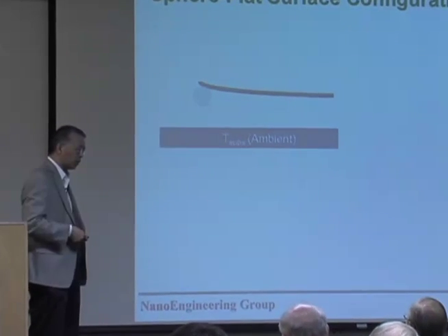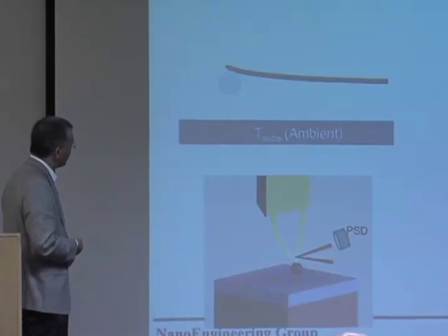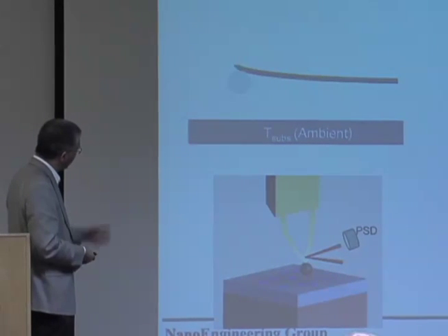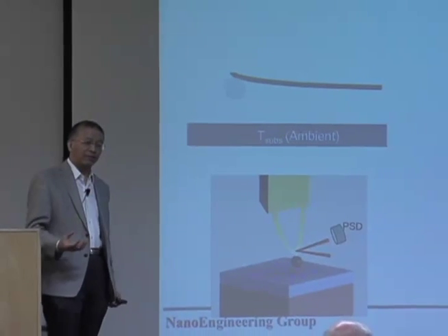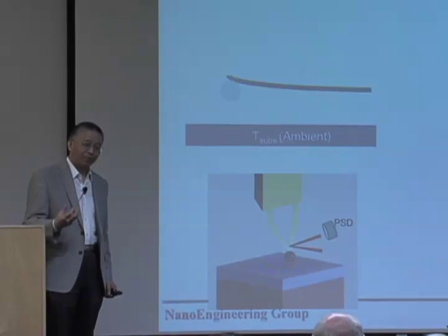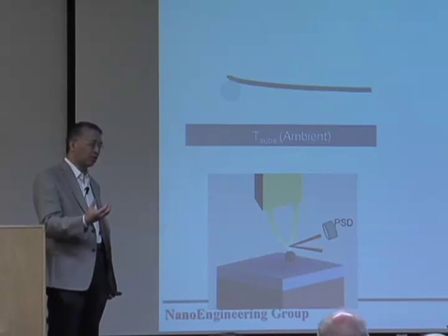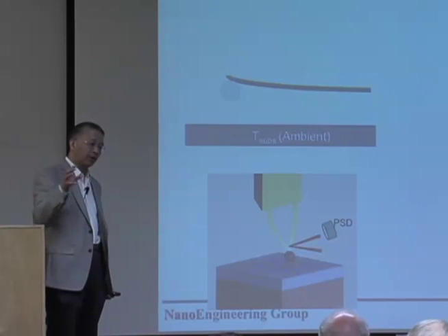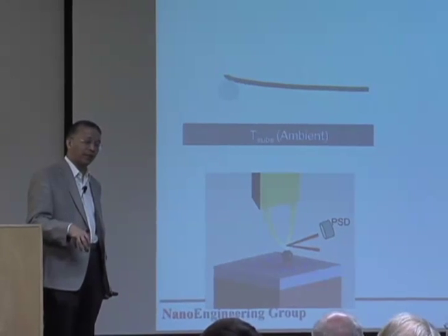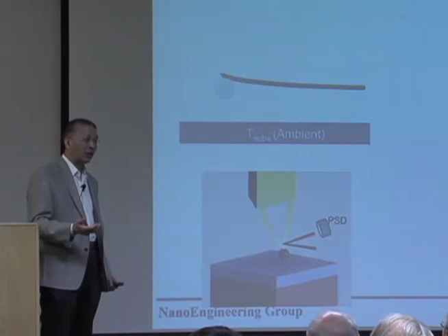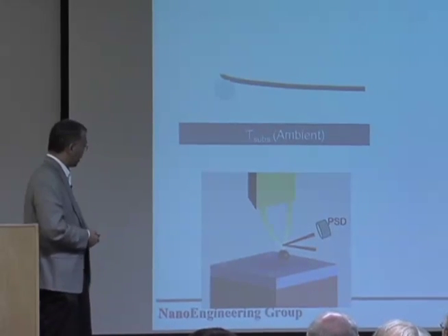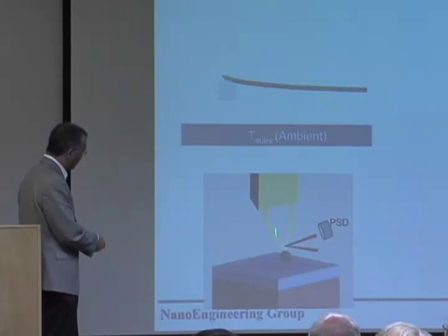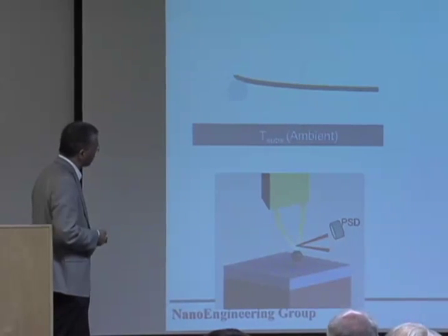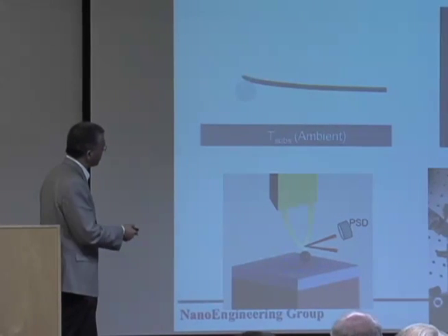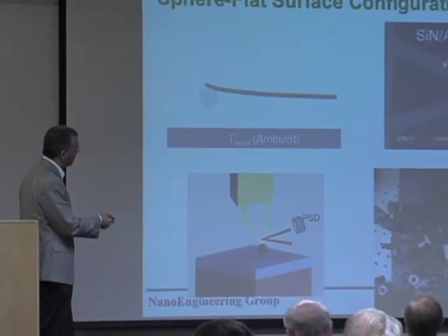as we move closer, the cantilever will bend, and that's what we're trying to do. But it turns out if you use the AFM, it won't work, because once the distance goes to 50 nanometers or 100 nanometers, the van der Waals force will just slap the cantilever onto the substrate. So we had to reset this up and turn it 90 degrees, and that way we can avoid the force effect. And so this is the typical experimental configuration we use.